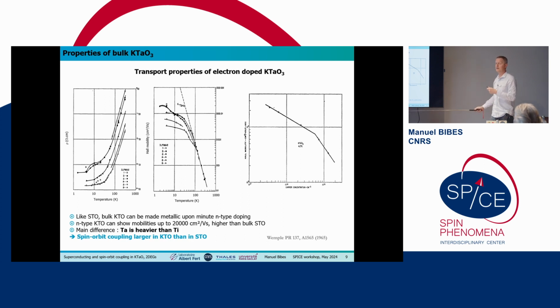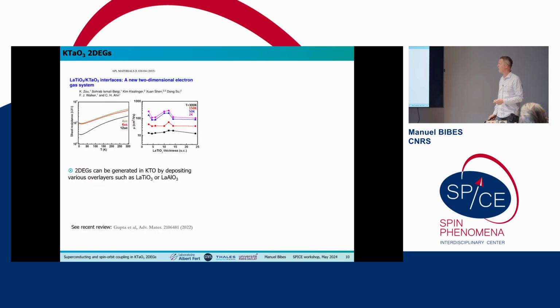But in terms of the other ingredients, spin-orbit coupling, it's in principle going to be more interesting than strontium titanate because tantalum is much heavier. It's a 5d element, much heavier than titanium. So you should expect to have stronger spin-orbit coupling effects. Of course, if you want to have Rashba spin-orbit coupling, again, you need to build an interface. So you are not going to see it in bulk potassium tantalate.